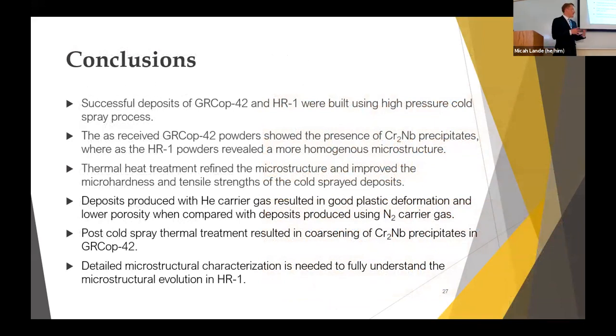In conclusion, wrapping up, we were able to look at the powder particles and get a good characterization of them. We were able to look at some of those properties and how they vary between the two materials, again falling back to exactly what we expect them to be. Then going through the cold spray process, we were able to look at how those properties change from the powder state to the solid state. And we were able to see some of the mechanical properties of that as well.